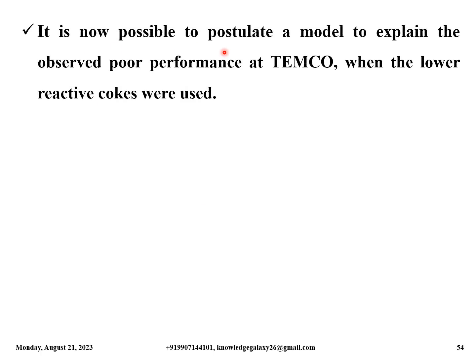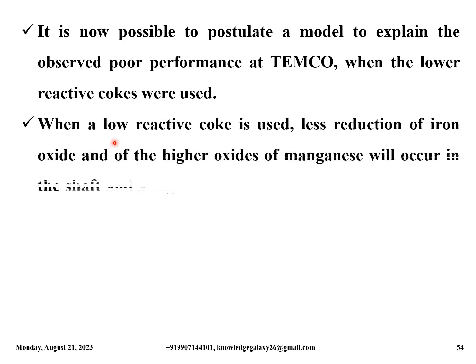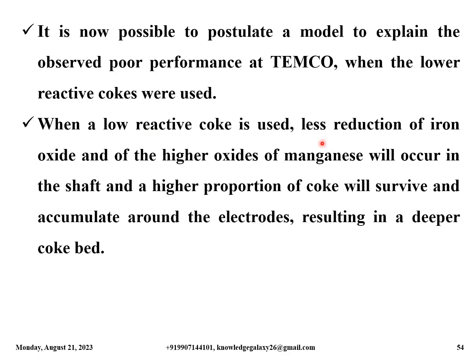It is now possible to postulate a model to explain the observed poor performance at TEMCO when the lower reactive cokes were used. When a low reactive coke is used, less reduction of iron oxide and of the higher oxides of manganese will occur in the shaft, and a higher proportion of coke will survive and accumulate around the electrodes, resulting in a deeper coke bed.